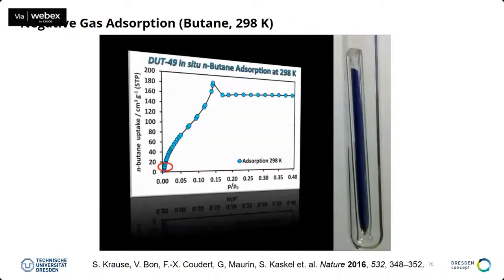So he filmed the sample, and now you can see the sample is basically approaching this very strange negative gas adsorption step, and then suddenly what is happening is that there's gas coming out of the sample. So it comes out of the central part of the sample, and it lifts up the sample, so the powder starts to move, essentially. It's moving up. And then after the step, it's moving down again. And you see that it's even moving down deeper than it was located before.